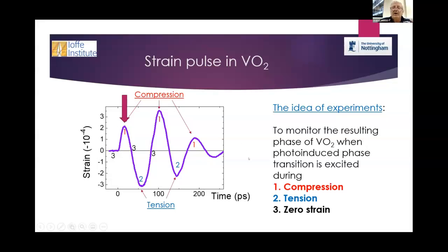And then we excite it when there is a tensile part. We are also interested in what will happen with the phase transition when we excite it at this time. And then we excite it, say here—one may think nothing should happen, but it's not very clear, because maybe nothing will happen. But after this, the system, as I said, is in a metastable state, and there's still strain, compression and tensile coming. What will happen then?